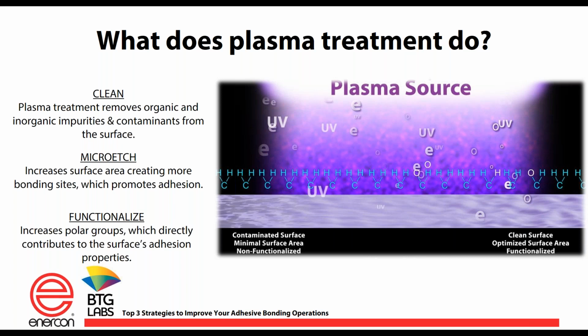Also, you can see on the left side, we've got a relatively smooth manufactured surface. And as it goes through the plasma on the right side, you'll see that it's been micro etched. Now we're talking 5 to maybe 20 nanometers. So this is not something that's visible to the naked eye, but it does increase the usable surface area that you have. And the more surface area you have for bonding, the higher the bond strength.